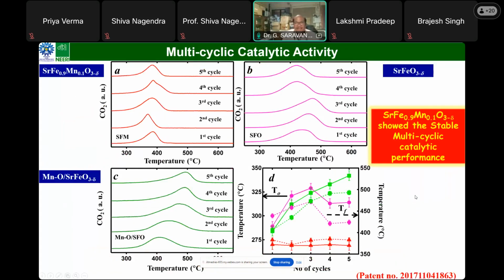Again, we need to check the durability, and the manganese substituted catalyst is showing almost the same potential. What we have done is take the catalyst and mix in the diesel particulate matter. After the first cycle, we mixed again, and we continued like this. We repeated these experiments and checked, and the performance stays almost within the desired window.